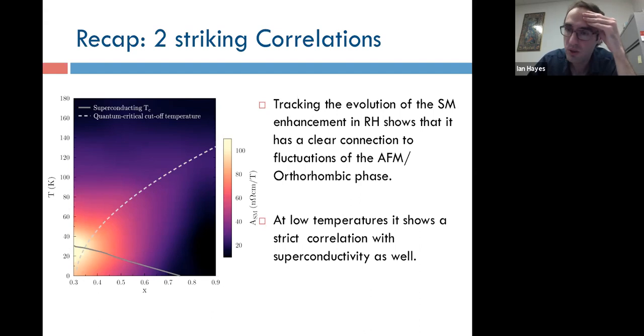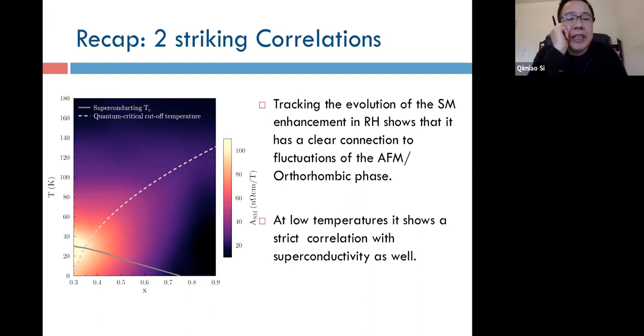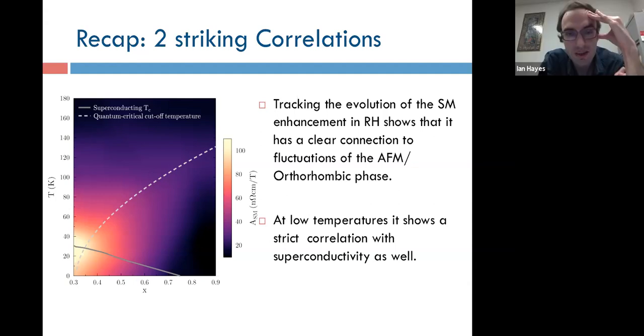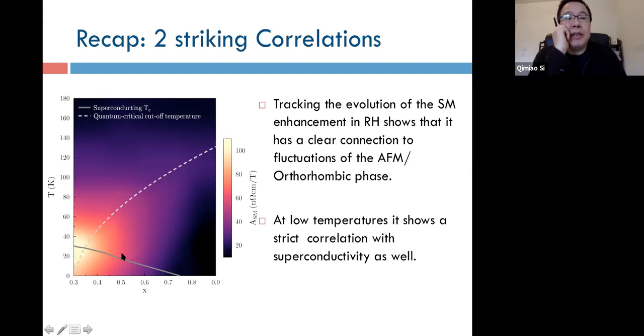Can you describe what accounts for that difference between vanadium doped chromium and the heavy fermion material? Yeah, it's tied up with the very drastic Fermi surface change on the two sides of the quantum critical point that happens in a heavy fermion system that doesn't happen in a more conventional spin density wave quantum critical point. Yeah, to me, what's most striking here is that it doesn't seem to sharpen up totally, that no matter how low you go in temperature, there's some finite width here, which seems to characterize the superconducting dome. Which might be related to the truncation of the quantum criticality on the temperature axis.